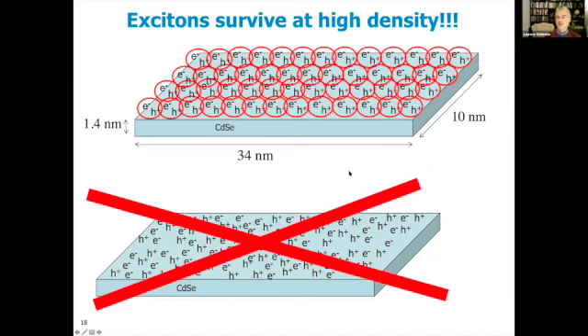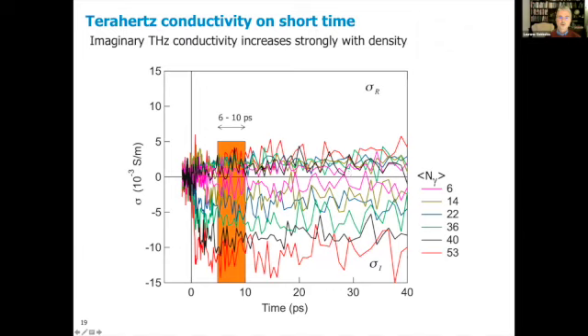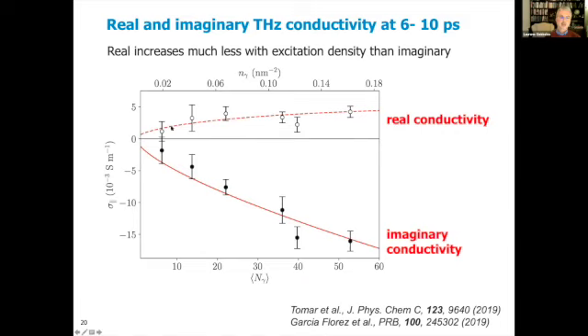But we wanted to establish that a little bit more, so we did our terahertz conductivity measurements for a larger number of absorbed photons per nanosheet. We averaged between 6 and 10 picoseconds after the pump pulse, to reduce the noise level a little bit. And then we get these results. The real conductivity is shown here. That is due to free charges, which increases a tiny little bit. But the imaginary conductivity, that's a close to linear increase with the number of absorbed photons per sheet. The curves shown here are from a theoretical model that I'm going to explain in the following.